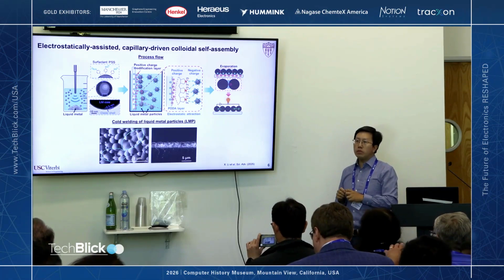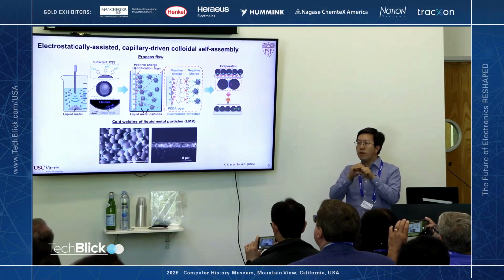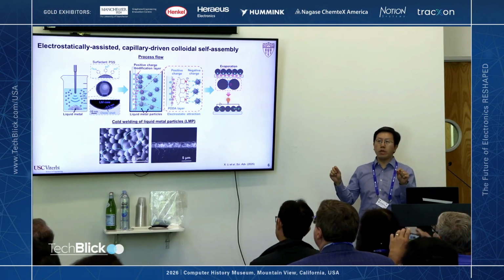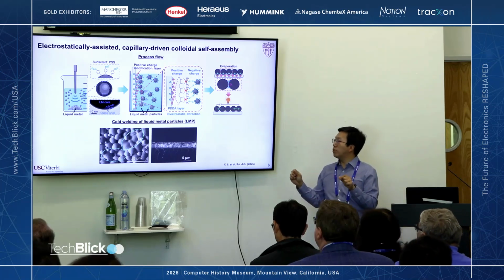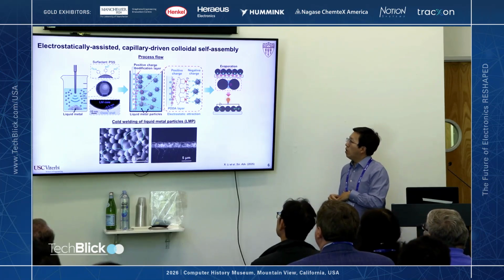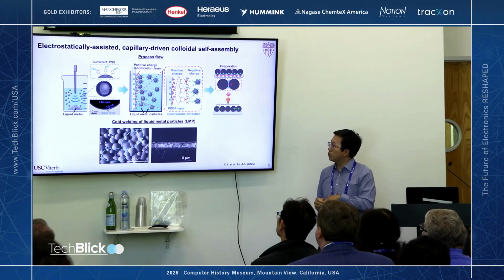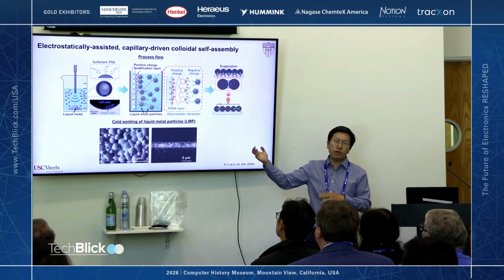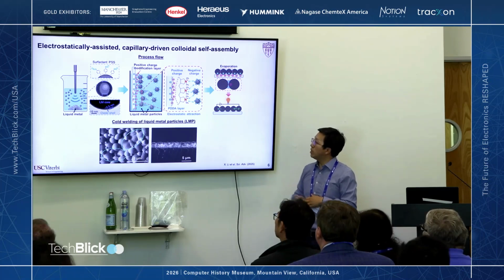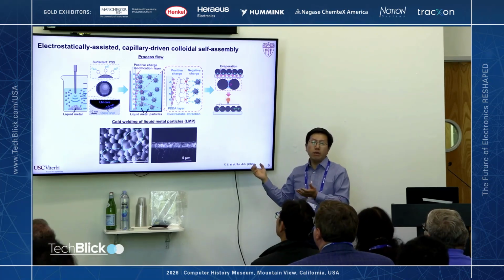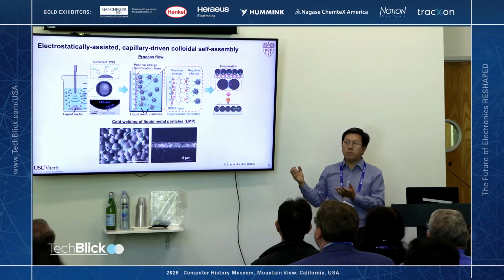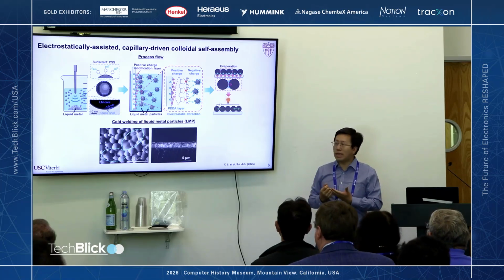First, I'll talk about how we can form a single layer of highly conductive liquid metal particles. Here we need to do two things. First, we need to form a very thin film, which is very hard to do for liquid metal already. Second, we want to make sure that they're conductive. We can generate liquid metal particles through ultrasonication in a beaker. That's a very standard process, nothing new. You can see each particle has a nanoscale oxide skin, which makes it basically not so conductive.